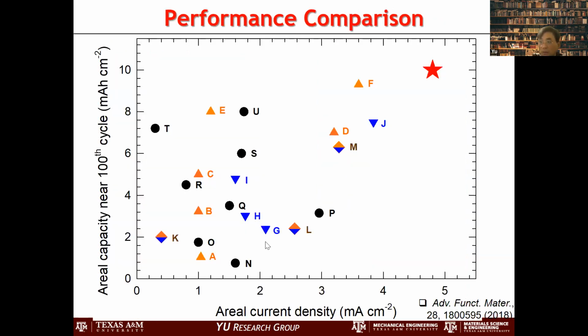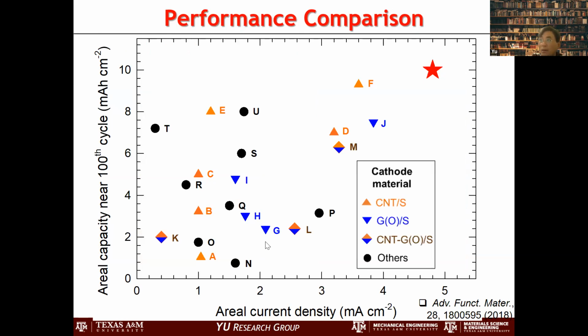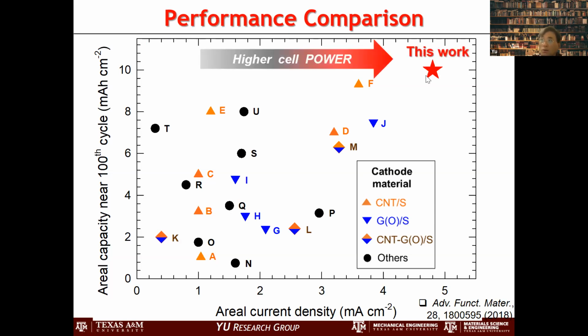Okay, so we made those materials, and we actually made a battery, and we tested all the performances. And so this is an areal density, and this is a capacity near 100th cycle. These are all literature value. These are our value. And so we have a much higher cell power, and we have a much higher, say, cell energy. So we actually demonstrated that our battery cell actually works pretty well.